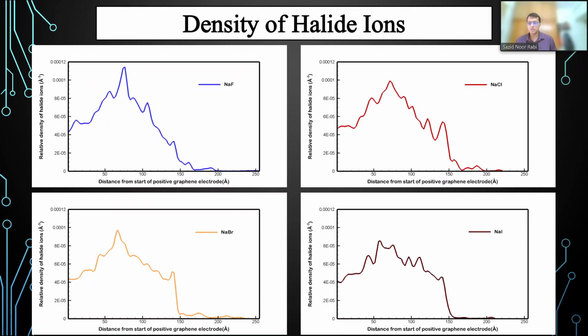Here we can see the halide ion densities. Density fluctuations are seen between 0 angstroms and 150 angstrom, which is the porous portion of the crumpled graphene, indicating that negative ions have successfully entered the pore. After this portion, density values go down to the nominal density values in the bulk solution. Region up to this is known as the diffuse layer.